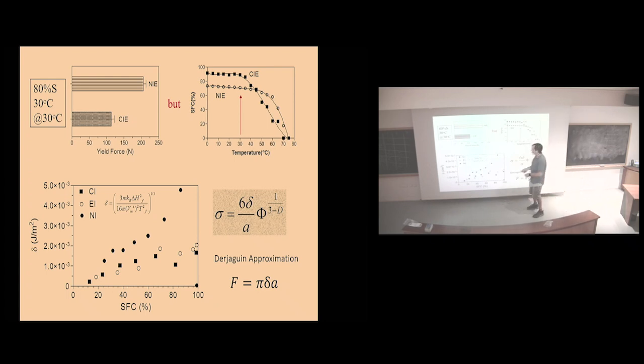So what we did is like, okay, let's find the culprit. We put together everything we've learned in this lecture and did that Fischer-Turnbull analysis to get the crystal-melt interfacial tension, just to see if there's some effects in there. These are different amounts of the fat in the oil to get the whole range, for many different samples. So what's this one here that is higher? This one here is the non-interesterified. So we interesterify, we randomize molecularly, so now everybody's more the same as opposed to very different, right? Solid and liquid. And look at that, we lower the interfacial tension between the two.